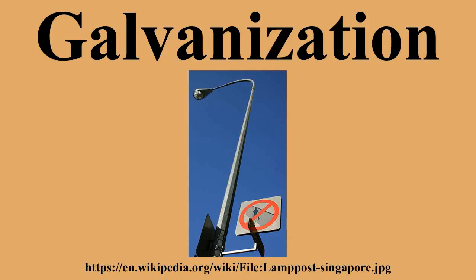The size of crystallites in galvanized coatings is a visible and aesthetic feature, known as spangle, by varying the number of particles added for heterogeneous nucleation and the rate of cooling in a hot-dip process. The spangle can be adjusted from an apparently uniform surface to grains several centimeters wide. Visible crystallites are rare in other engineering materials.